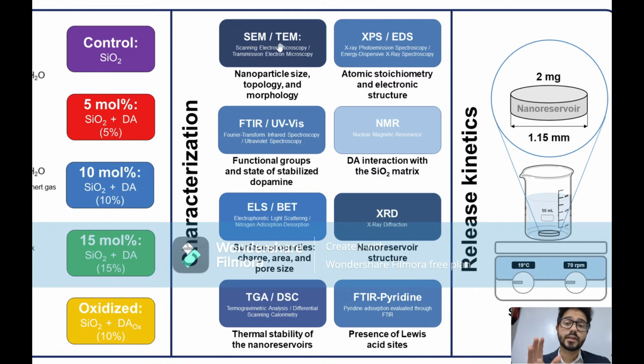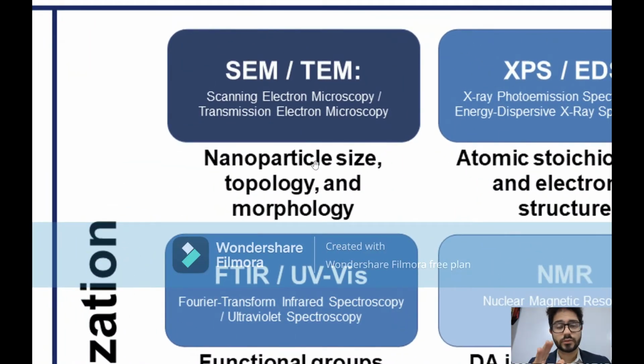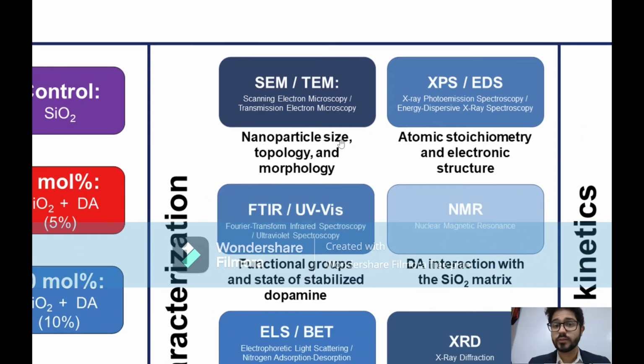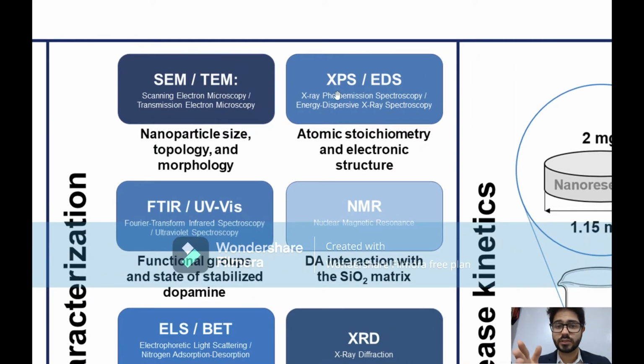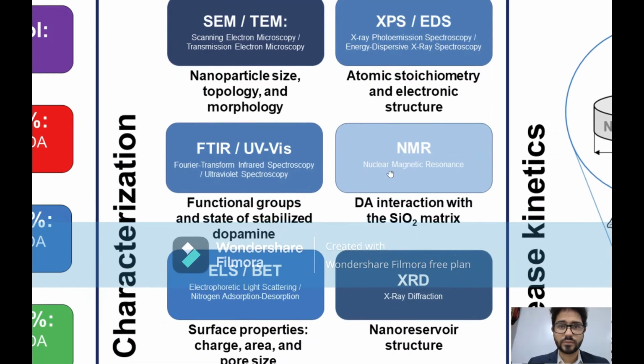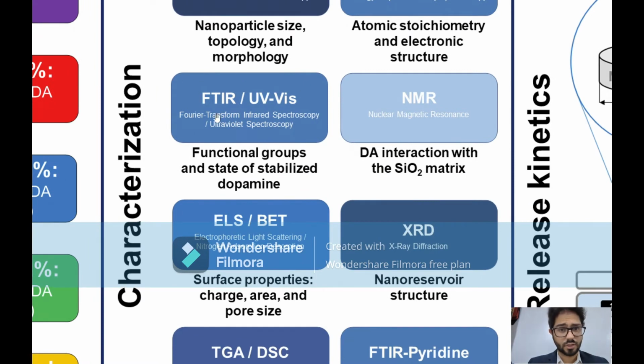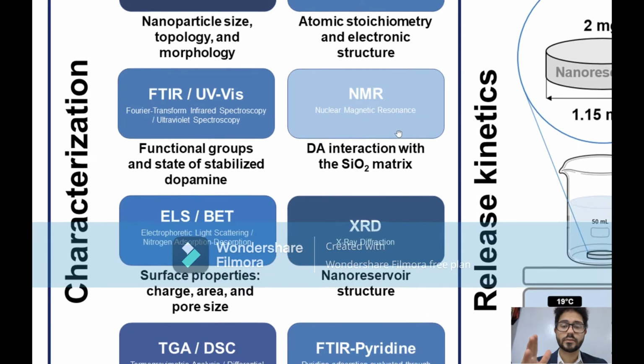First, scanning and transmission electron microscopies allow us to know the size of nanoparticles, their topology, and morphology. Next, we evaluated their chemical composition. X-ray photoemission and energy dispersive spectroscopies showed the atomic stoichiometry and electronic structure, and Fourier transformed infrared and ultraviolet-visible spectroscopies showed the functional groups and, very importantly, the state of the stabilized dopamine, which is of utmost importance as mentioned above. Next, the physical properties were evaluated.